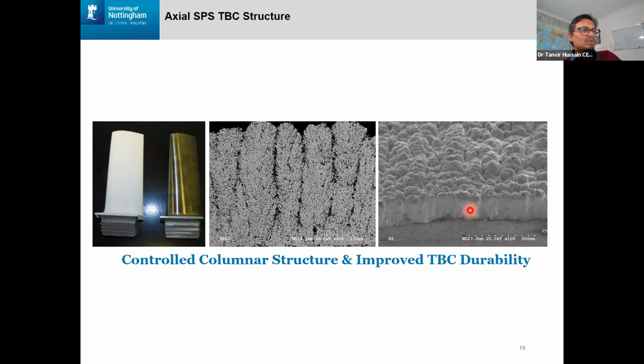The reason it produces the columnar structure is that the fine nanoparticles tend to follow the plasma jet stream. When you have asperities on the substrate, those particles travel along that plasma, hit those asperities, and start depositing and producing that column. So just by altering the particle size, you can alter the microstructure that we get, which is highly desirable.